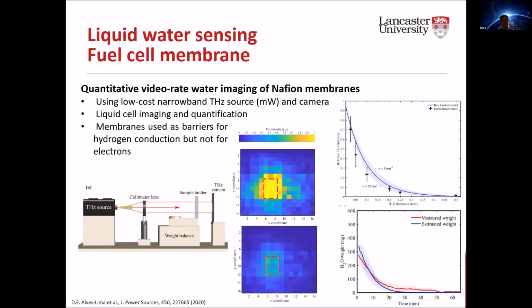Now, liquid water, we know, is a material that is very polar and so strongly absorbs terahertz. So if we put a detector after liquid water, what we would expect is that there will not be much terahertz transmitted because it's all absorbed. And that's what we see in this little diagram here, as opposed to when the sample holder is filled with air, for example, so free space, whereby all the terahertz will just transmit through and we get this lovely yellow spot.